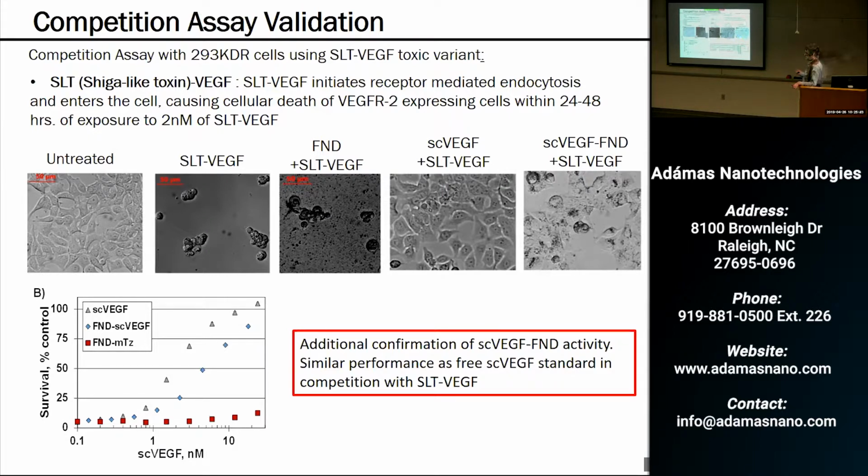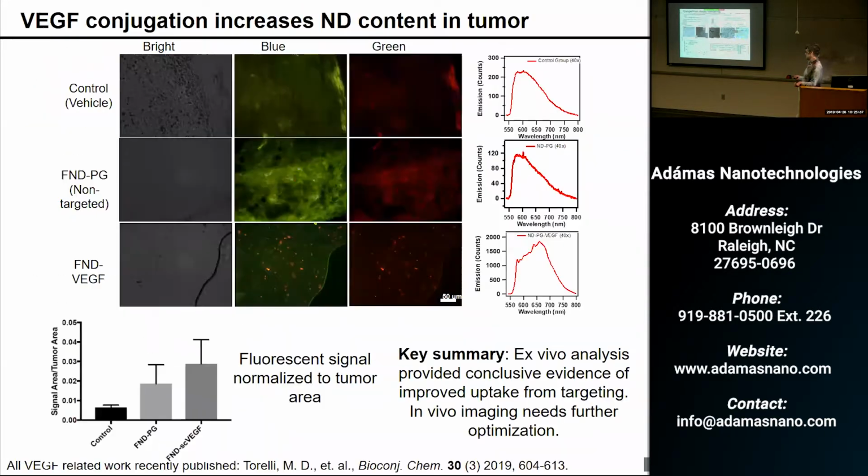But okay, we can see this 2-color imaging, and there have been some other demonstrations of 2-color, but this is one of the first where it's actually been done with confocal microscopy and not with some electron beam excitation or cathodoluminescent microscopy, or in one case they're using IR emitting and NV emitting. So this is green and red emission from the NV0 and NV- centers.